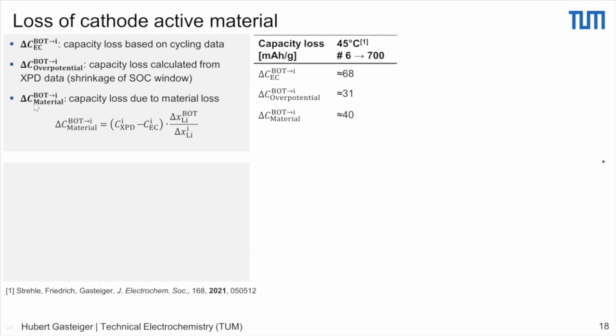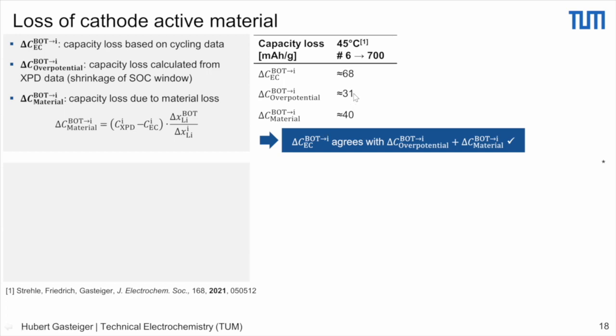And then we can calculate what is the material loss. This you could calculate from the difference of the capacity based on the SOC window minus the electrochemical capacity normalized by the relative utilization of the material. So the details are really in the paper. And that would come out as 40. Now, of course, those two would have to add up to this. And as a matter of fact, it's pretty good, right? So the sum of those two is 71, this is 68. So we have an error of about 5%.